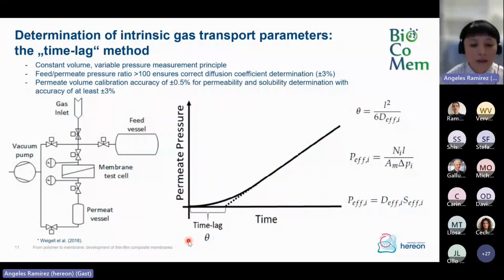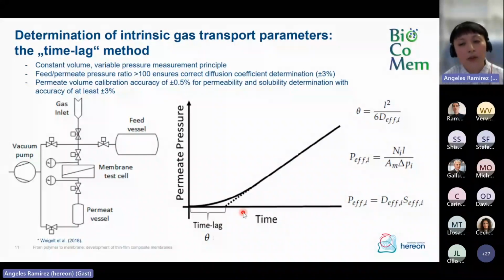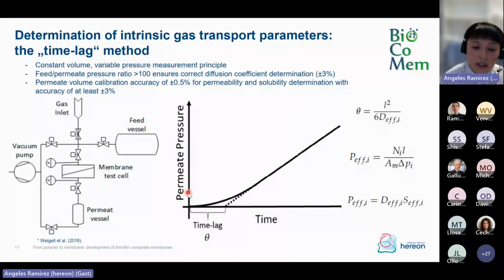And now when we have this polymer film ready, we proceed to characterize it via the time lag method. This method consists of exposing the polymer film to a constant pressure of a given gas, and then observing how this gas diffuses through the known thickness of the film, as we can see here. And this is done by observing the permeate pressure in a calibrated permeate volume, after previous evacuation of the apparatus.